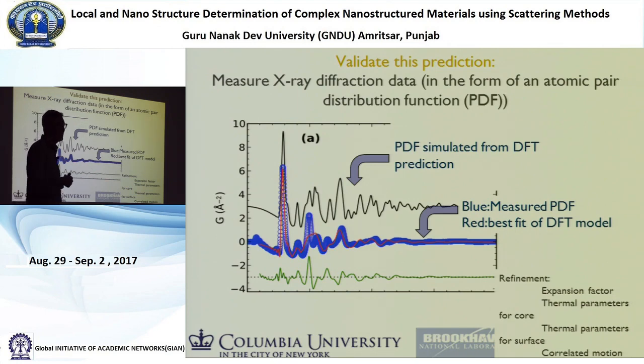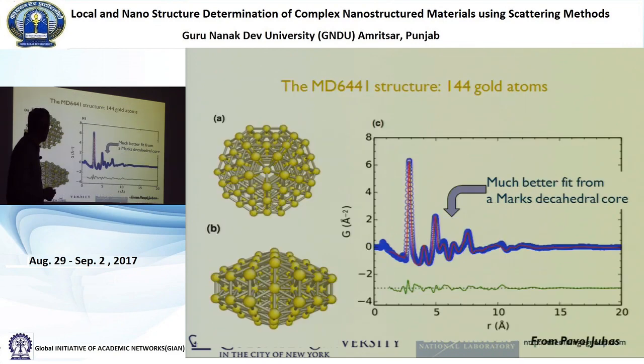So the DFT prediction was wrong. So that actually goes to show that DFT, as powerful as it is as a computational method, is not always getting things right. And you have to check it with experiment. So we started model building. And there's really two ways that gold clusters go. They either go icosahedral or decahedral. Decahedral is actually a close-packed form. So the local arrangement.